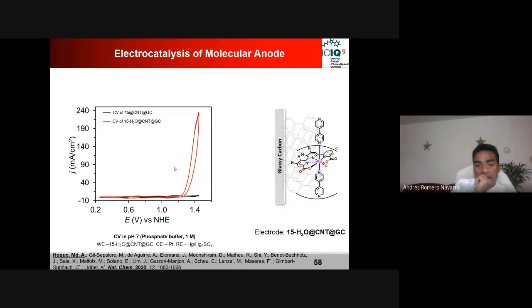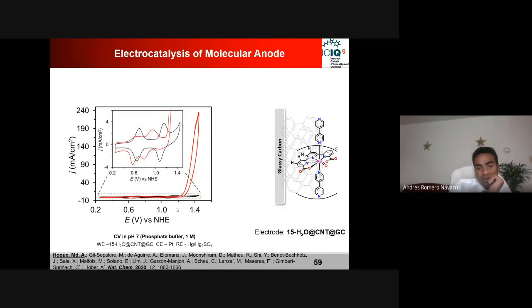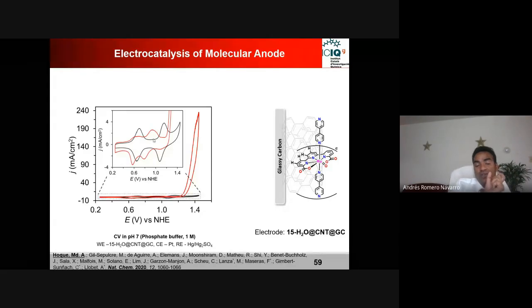And then, if you look into the close view, the black one is our starting material, right? The starting material is nothing but the 7-coordinated compound without coordination of water. But the red is showing that now we have this coordination of water at high valent oxidation state. This water is forming a ruthenium water compound, which is actually forming ruthenium oxo. And now these two redox couples are related to the ruthenium 2/3 and 3/4 redox couples.